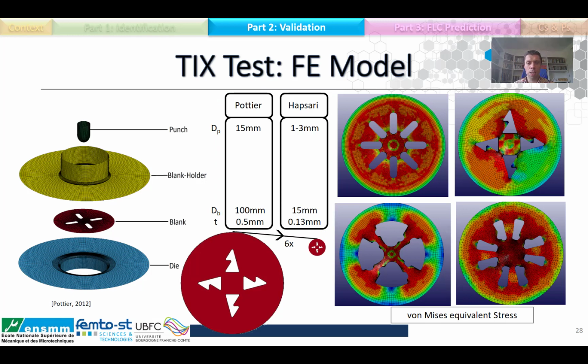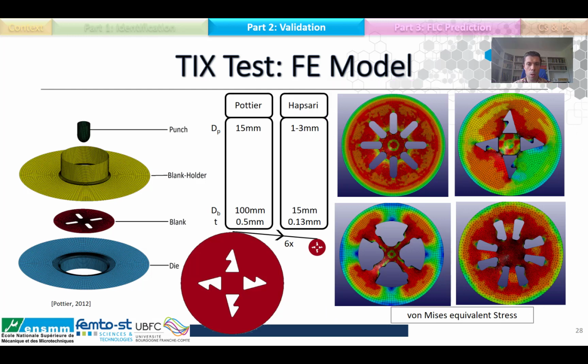So the goal of choosing this test is to validate the material parameters obtained from the micro-indent test, because the advantage of this test is that by modifying the aperture in the blank, we can obtain different solicitation fields, as illustrated here with these 4 examples. Therefore, we can validate the identification by the micro-indent test on different loading cases by only changing the specimen. The set of TIX device consists of a blank holder, die, a blank, and a punch.